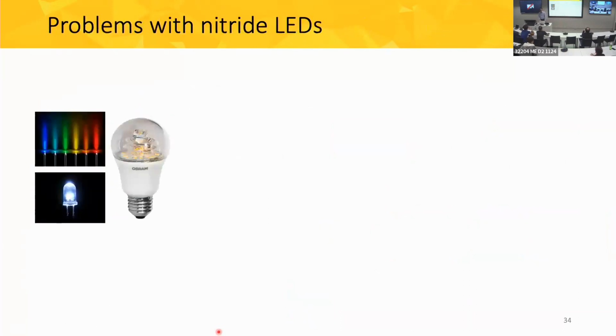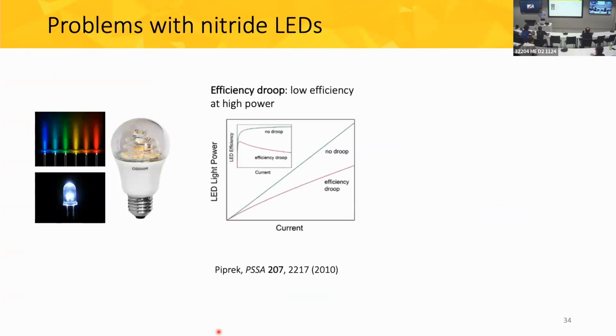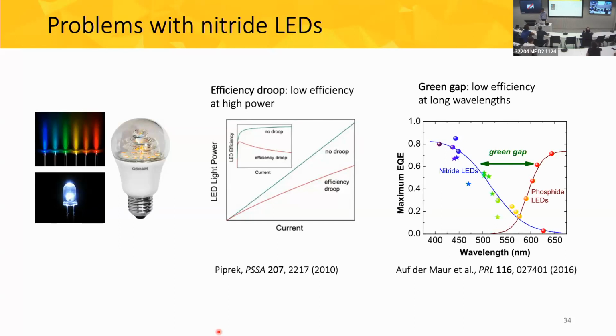Auger-Meitner recombination, though, is more famous for its contribution to LEDs, in particular the nitride LEDs in the visible range, because they have two major problems. One is that their famous efficiency of more than 80% occurs at low power, and if you go to high power, the efficiency drops. This is known as the efficiency droop problem of the LED. The droop becomes even worse as you go towards the green, so efficiency is high for violet and blue LEDs and drops when you go to green and yellow.